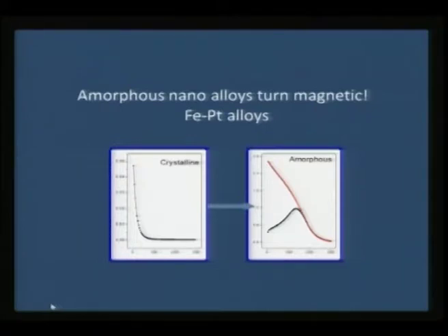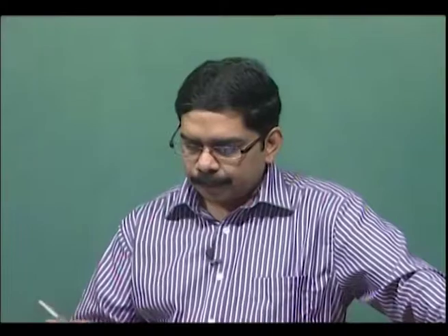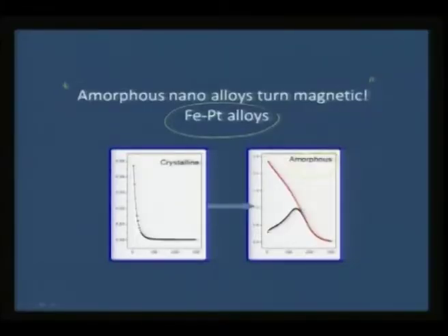In today's lecture I would like to concentrate a little bit on iron platinum alloys. As I have titled it here, the amorphous alloys of iron platinum, when they are prepared sonochemically, actually turn magnetic. What is unusual here is that in the iron platinum phase diagram, which we will see shortly, there are regions where, when platinum is doped across the series, there are some limiting compositions where the alloy turns non-magnetic. So, when there is a magnetic, non-magnetic phase, usually the properties would vary, but what we see in amorphous alloys of iron platinum, irrespective of the composition of platinum, everything is turning magnetic, and this is one of the view graphs which shows that amorphous alloys are turning magnetic, and the Tc seems to be somewhere around 240 Kelvin.